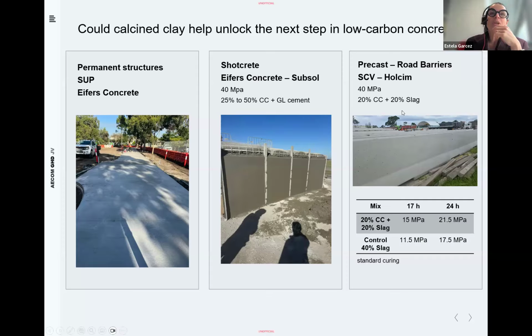And what's happening with precast as well, we did a bit of work with SCV and Holcim and got some 20% calcined clay. They do have 40% slag mixes that they supply in their product range, but we got excited with that initial ramp up of strength at 24 hours by replacing 20% of that slag with 20% of clay using standard curing.